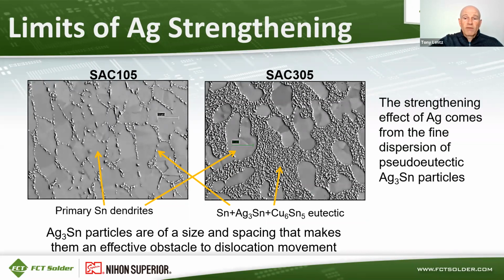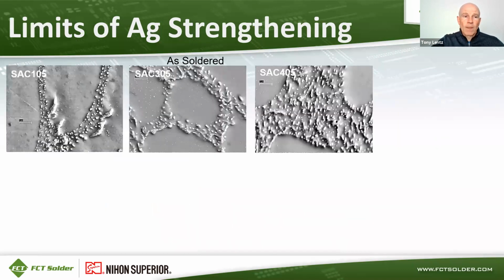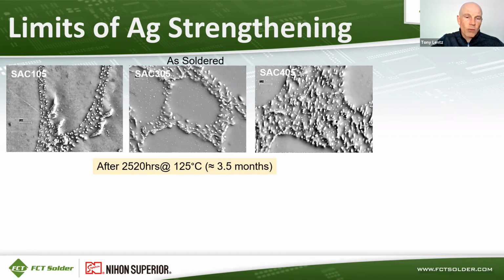And that strengthening effect comes from that fine dispersion of the pseudo-eutectic Ag3Sn particles. Here's cross sections of SAC 105, SAC 305, and SAC 405 as soldered. And then those samples were aged to 2,500 hours at 125 C. So we did isothermal aging. So that's about 3.5 months at that temperature.